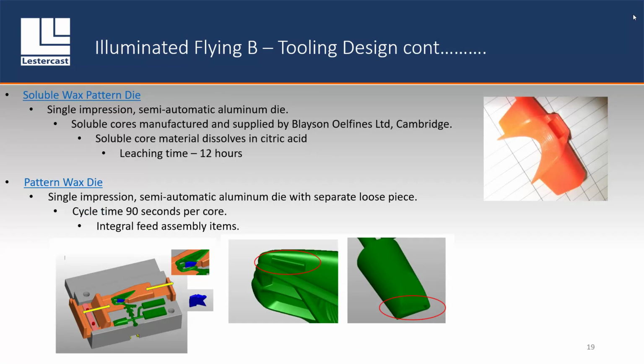I mentioned the soluble wax die. So the die itself, again, was designed and manufactured by Arthur Jackson's. The soluble cores are actually manufactured by another supplier into Lestercast, Blayson. I don't know if anybody knows of Blayson, but they produce all of our soluble waxes. And we went down the soluble core route because of the complexity, effectively, of the wing area. It wasn't easy to produce a tool that would make that in a conventional way. So for quite a few years, Lestercast have used this technique, which is a soluble core material, and we've got some soluble cores as an example on the table.